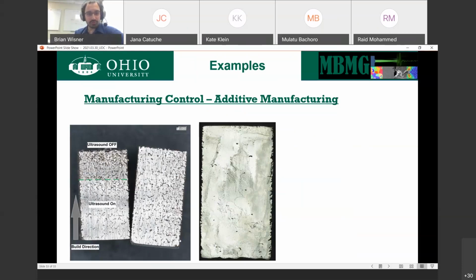When we turn it off, when we're directly on it, we do see a change in surface porosity. Once we polish this down past the surface into the base part of the material itself, we don't observe any obvious real changes in porosity behavior. There's a few pores here and there, and it seems fairly consistent across the material.